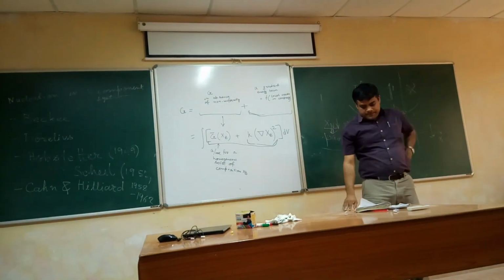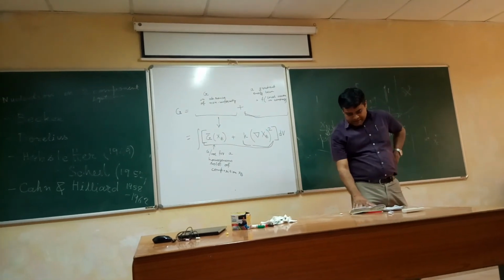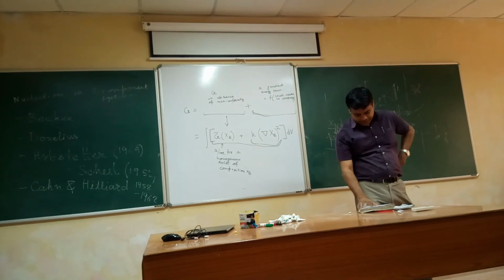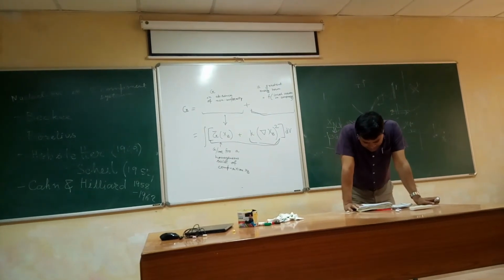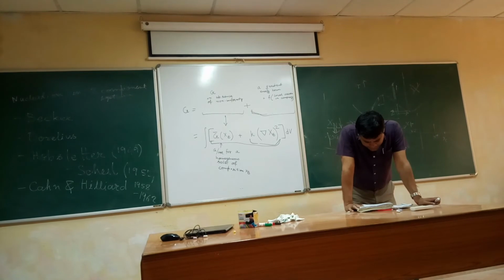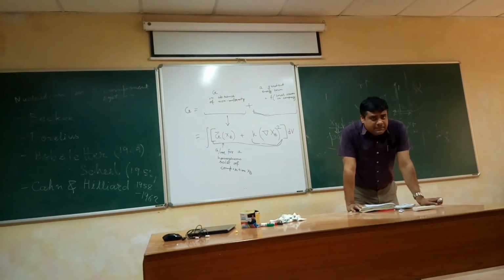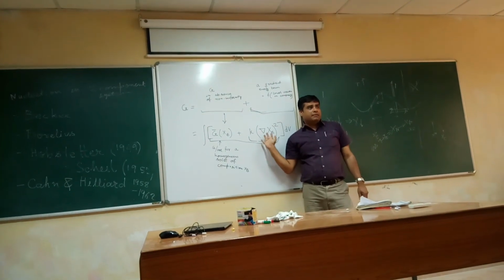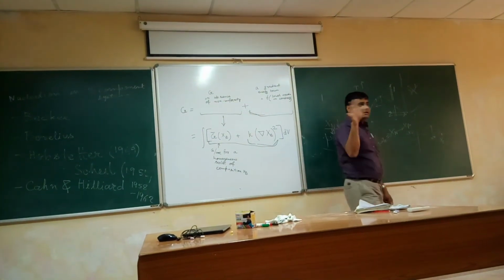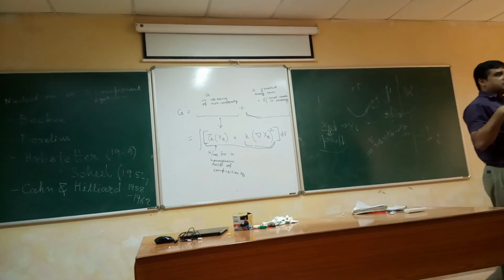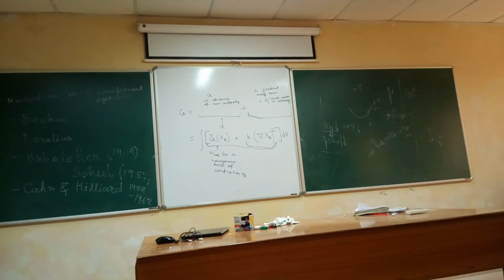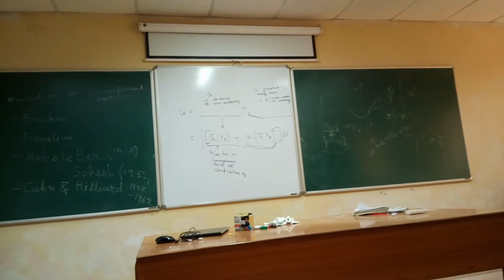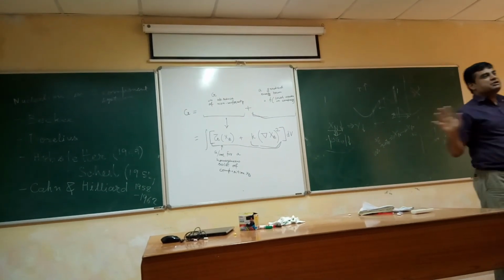And also the atomic size, the two components have the same atomic size. That is because we are taking local fluctuation, and any variation in composition should not give any additional strain. So atomic size of the product and the matrix are assumed to be constant.